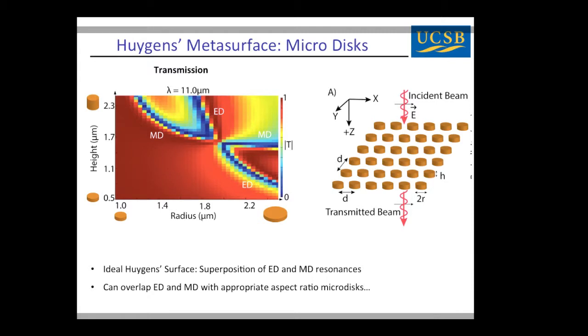We can look at how the transmission resonances change as a function of both radius and height, or really the relevant factor here is the aspect ratio. Okay? So what we should see here is that there is a dip in transmission from the magnetic dipole mode, and similarly one from the electric dipole mode. But when they intersect in the center, because of their relative interference, you actually get our minimum reflection and transmission becomes unity transmission. Okay? So what Prasad did was look near this region.